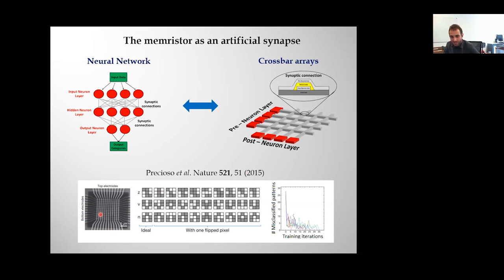And then what they do is they adjust the weight of each of these synapses of the crossbar array, so that the crossbar array is able to identify, for instance, this image. This architecture will be able to tell you if this looks like a Z, like a V, or like an N. It has 3 different categories. So what they see is that they keep training the network, and the more they train it, the fewer failures the neural network makes. So the number of misclassified patterns goes down as you train the neural network, and goes down actually below 1%. So the neural network can say, this looks like an N. And so this is a paper from 2015.